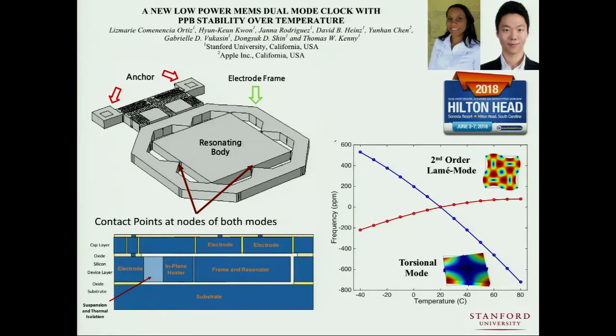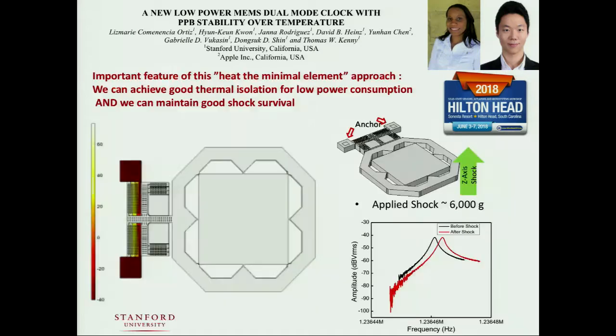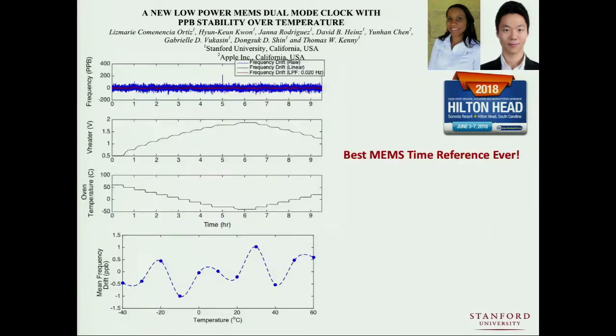With the right doping, this lame mode has a flat spot at around 80 degrees C, so we can ovenize at that point. And the nice thing here, since we're suspending the minimum amount of stuff, it's pretty robust. We can have low power. It takes about 20 to 30 milliwatts to heat this thing, and it'll survive 6,000 Gs of shock without breaking. How many OCXOs in the room can survive 6,000 Gs? I don't see any hands. This can, and it's because we're only ovenizing a few cubic microns of stuff instead of millimeters or centimeters, and that helps a lot. So this is how the performance of this device looks.